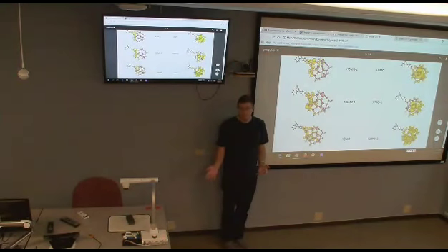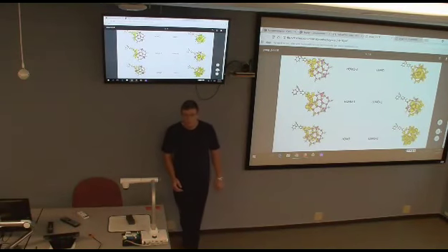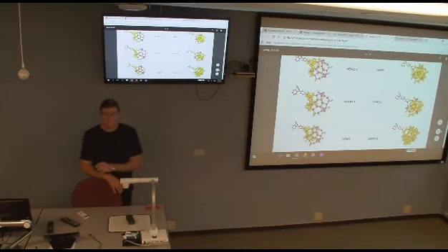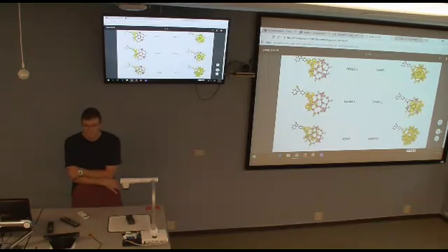But in your case, again, you can probably easily put it in a quantitative way, right? I mean, you do your TD-DFT calculations just to see the effect of excitonic effects. Actually, you can do it for the functionals, right? You can do just ground state calculations. You don't really need to do spectra, right? Right. You just do ground state calculations again without optimization to have exactly the same geometry.